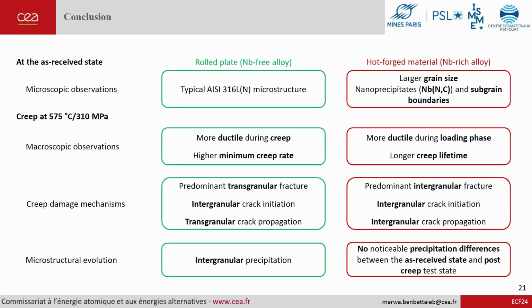So to conclude, we have two different alloys of 316 austenitic stainless steel that differ by their microstructures. During creep, the niobium-free material is more ductile than the niobium-rich alloy, which is not the case for the tensile loading phase. We have longer creep time and a much lower minimum creep rate for the niobium-rich alloy.